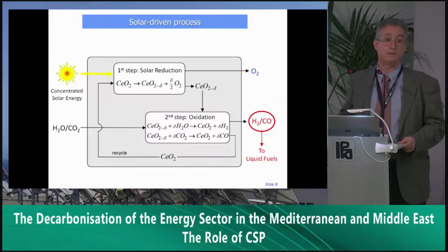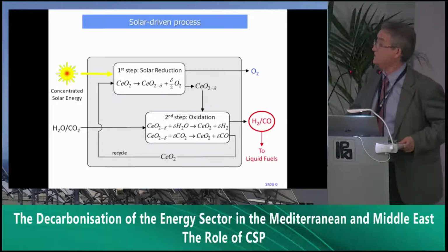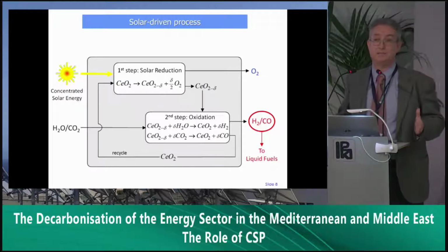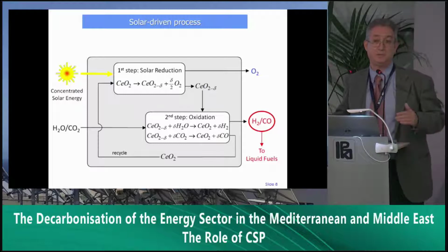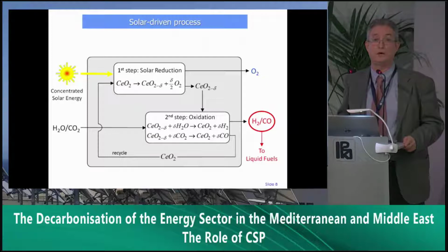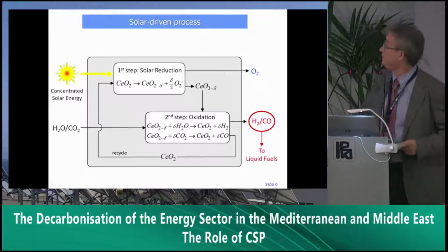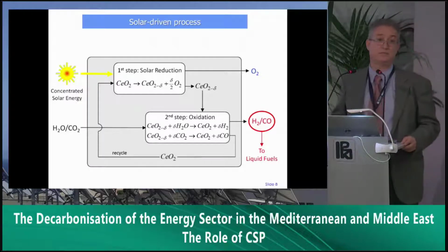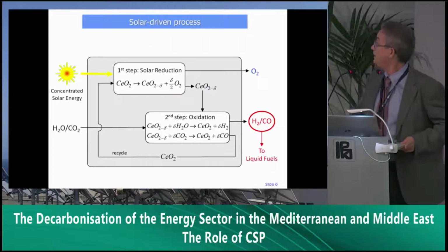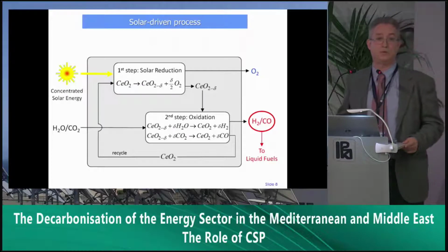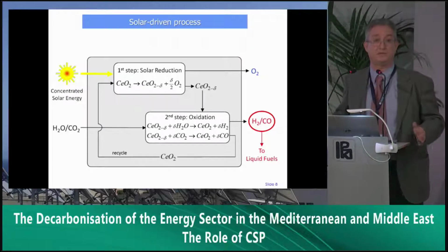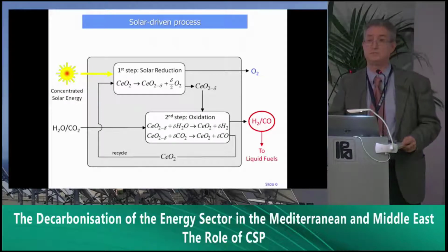this thermochemical cycle solution with 2 steps. This is improving the conditions a little bit, but you will see in my presentation that it is still not so easy. We are not requiring extremely high temperatures, but processes like this one based on ceria for the joint reduction of water and CO2, for example, need temperatures around 1,400, 1,500 degrees. This means also very high concentrations.